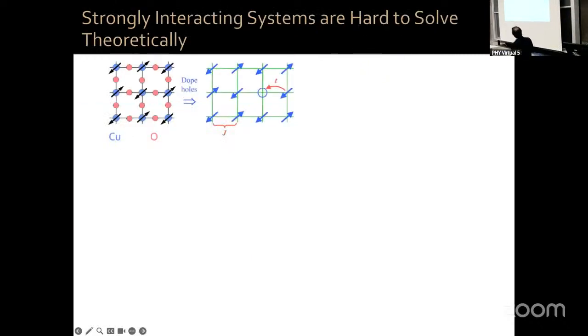So in the high temperature cuprate superconductors, all of the action takes place in these copper-oxygen planes. These are two-dimensional planes of alternating copper and oxygen atoms. Yeah? And if you grow the stoichiometric compound of a high temperature superconductor, you have 1 electron per copper atom. Now, in each of those copper atoms, you can put 2 electrons, but since we have placed only 1 electron, it should be very simple for electrons to just jump from copper atom to copper atom and conduct electricity. This should be a good metal in single particle physics.